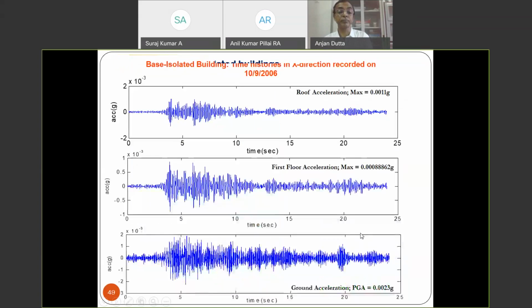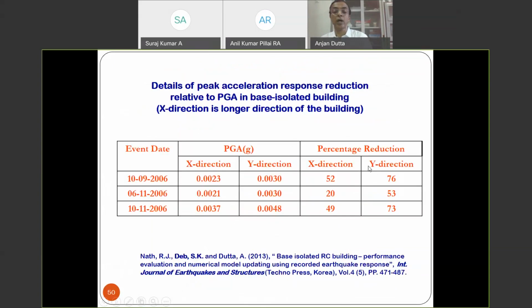meters. And if you see, there are some of the records which we have, because fortunately we had a lot of earthquakes. You can see that if this is the ground motion, having a peak value of 0.0023, it could reduce to as low as 0.001 at the roof level. So there's a huge reduction in the acceleration response. We have some records at 10/9/2006, 6/11/2006, and many others subsequently also. And you can see the percentage reduction, quite a good amount of percentage reduction.